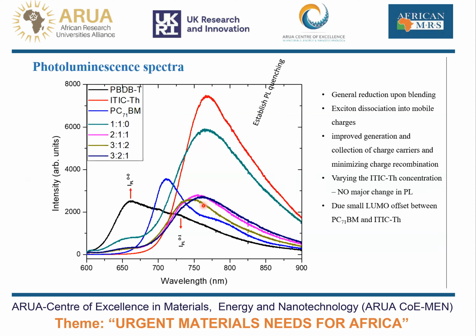So for instance, as you increase the fullerene material or increase the non-fullerene acceptor material, do you have a difference in PL quenching? We ended up not having any difference, because the energy difference between these acceptor materials is very close, and therefore you're not expecting an energy transfer or a charge transfer between an acceptor and an acceptor. So it means that what we have is just an energy transfer between a donor material and an acceptor material, which is either a fullerene or a non-fullerene material.